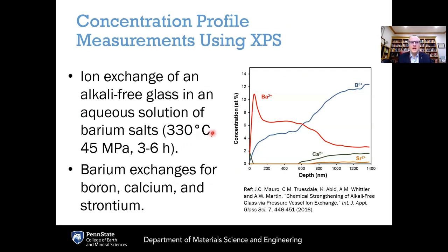This is an example that shows concentration profiles measured using XPS. This tends to probe much shallower regions near the surface compared to some of the other techniques, but you can still get in pretty far here. So this is a bit over a micron.